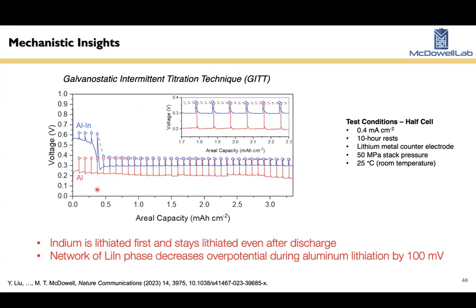So what you see basically is we're testing two different cells here. One has an aluminum indium electrode and one has pure aluminum. The pure aluminum has some overpotential. It's about 150 to 200 millivolt overpotential during the lithiation process, which is expected.